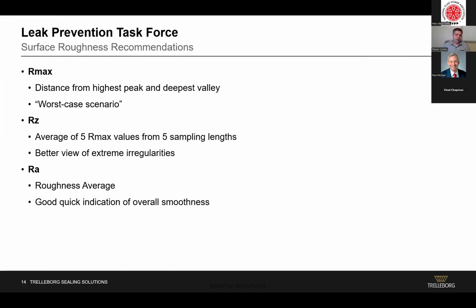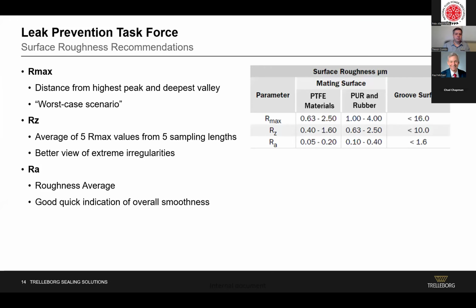And then Ra, we already talked about, is the roughness average. That is an important part of the roughness profile. And it gives you a good quick indication of the overall smoothness of the surface. And then we have recommendations for each parameter based on the seal material that you're using. So you can see with a PTFE material, you're going to want a little bit smoother surface than a polyurethane or rubber because it's more sensitive to that.